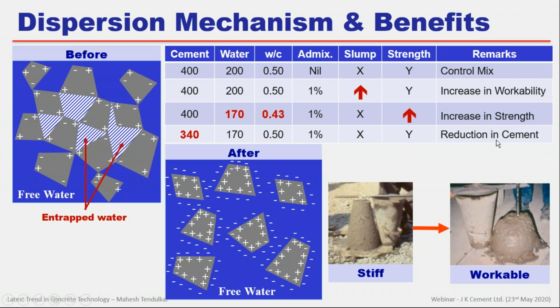So we get a reduction in cement content. And that is the reason I say, for M20, M25 and above, we must use the admixture, and only then can we produce good cohesive concrete at any site. So this is a simple dispersion mechanism of admixture.